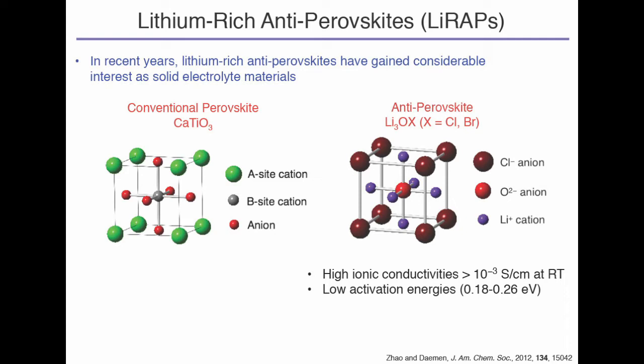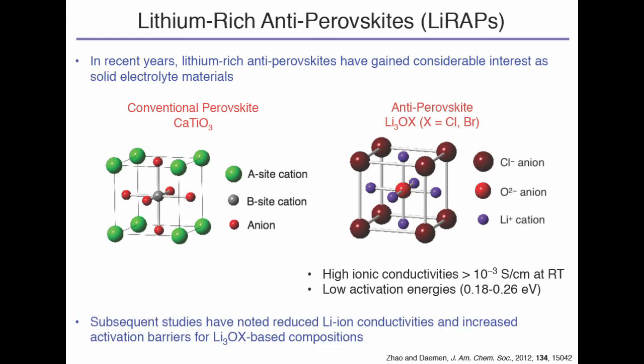Now, the reason this type of material gained so much interest in this JACS paper was because they reported very high ionic conductivities, 10 to the minus 3 Siemens per centimeter at room temperature, and very low activation energies. This paper claimed that these have the potential to be similar or better than the liquid electrolytes that we're trying to replicate. Now, subsequent studies on these materials have actually shown that these numbers are questionable. The ionic conductivities are now reported to be lower, and the activation energies are much higher. So we thought, what's going on here? There's a bit of a discrepancy within the literature.